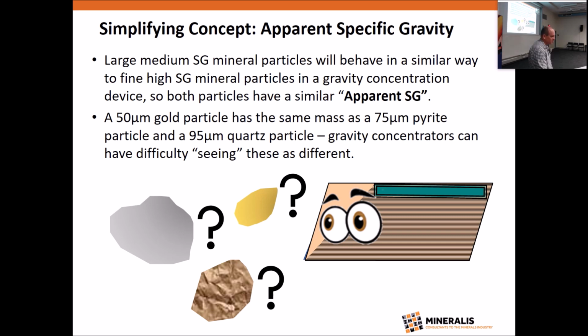So the next simplifying concept I want to introduce is apparent specific gravity. What this means is that large and medium or even light SG particles will often behave in the same way as small and high SG particles in a gravity concentrator. So a simple way of thinking about this is that both particles have a similar apparent SG. And some rough geometry tells us that if they've got the same shape, a 50 micron gold particle has the same mass as a 75 micron pyrite particle, or even a 95 micron quartz particle. And often these exist after comminution. So in the hustle and bustle of processing, a gravity concentrator can really struggle to see these particles as different. And include cyclones in that gravity concentrator group.